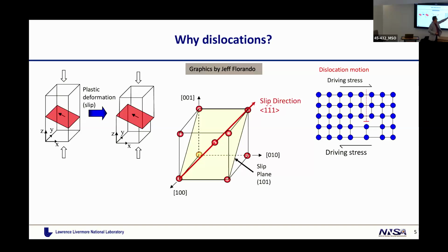There looks like a point here, right? This is the point, but in fact it is a line that propagates the slip along these planes. And therefore, why metals or other crystals are much less strong than this theory would have predicted is because you don't really break all the bonds at once, as required in this picture. You basically break one at a time, okay? And these lines are dislocations.